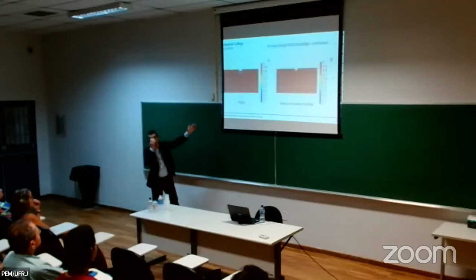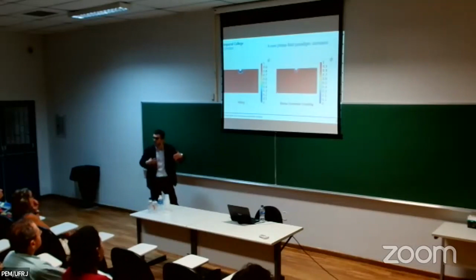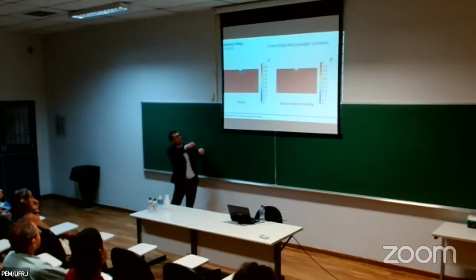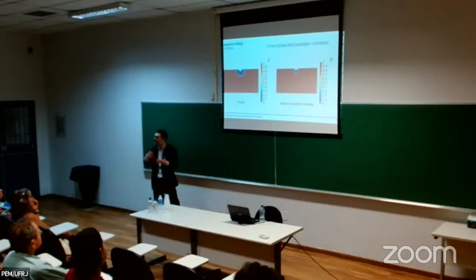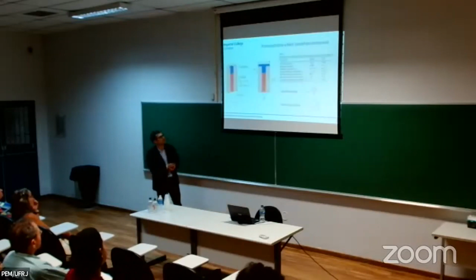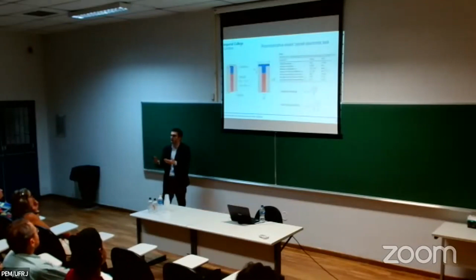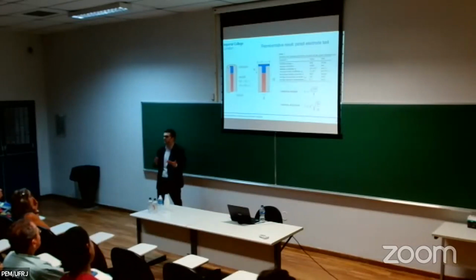As you can see here, it works. You can see the growth of a pit, and here you can see more of the stress corrosion cracking phenomena, the pit-to-crack transition. Here we're considering different conditions. There's no applied load here, and there's oscillation here, so we can naturally capture these different corrosion scenarios. And this is a classic paradigmatic example to show how the model can go from activation-controlled corrosion to diffusion-controlled corrosion, which are the two main regimes of corrosion.